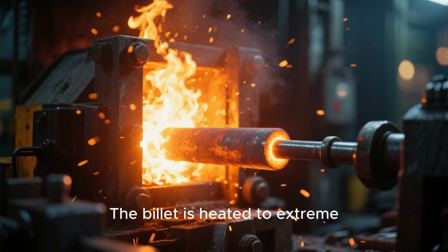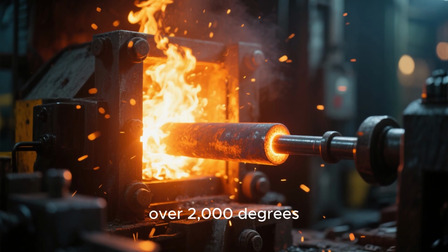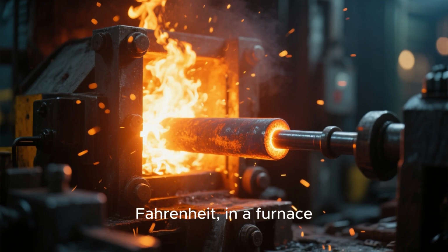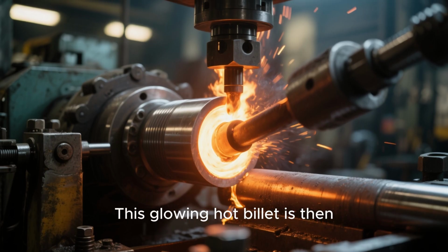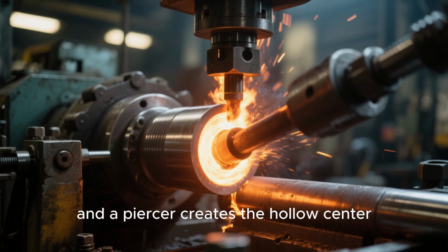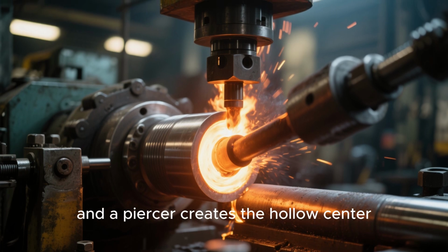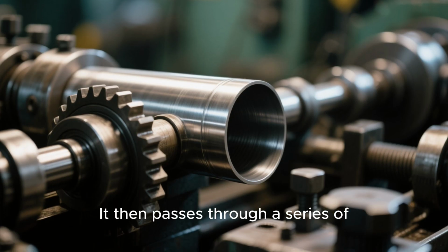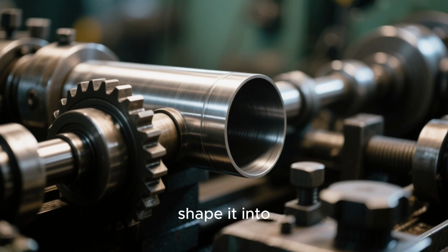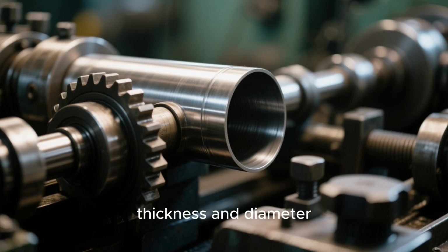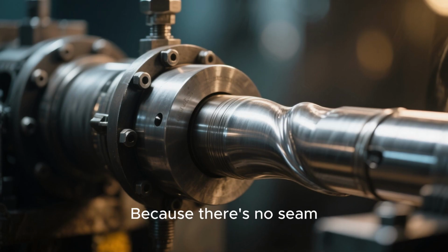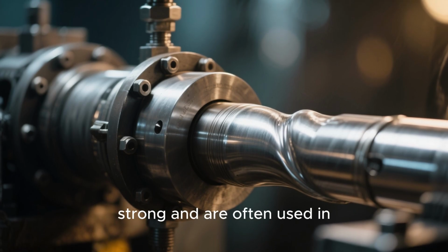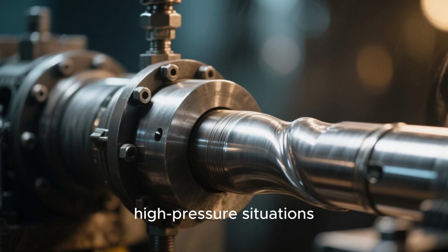The billet is heated to extreme temperatures, over 2,000 degrees Fahrenheit, in a furnace. This glowing hot billet is then rolled and stretched, and a piercer creates the hollow center. It then passes through a series of rollers that precisely shape it into a tube with the correct wall thickness and diameter. Because there's no seam, these pipes are incredibly strong and are often used in high-pressure situations.